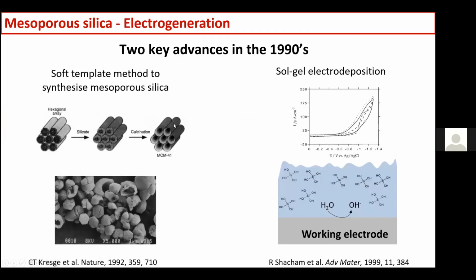So, for mesoporous silica and electrochemistry, there were two key advances in the 1990s. The first one is a Nature paper from researchers at the Mobil Oil Corporation. What they did is they mixed silica precursors and surfactant, cetyltrimethylammonium bromide in this case, then they found the right conditions to form micelles and condensate the silica around those micelles, and they formed MCM-41, the well-known mesoporous material. And here you have a SEM image of these mesoporous particles that were formed in this way. So this was a new way to make mesoporous silica using a surfactant.